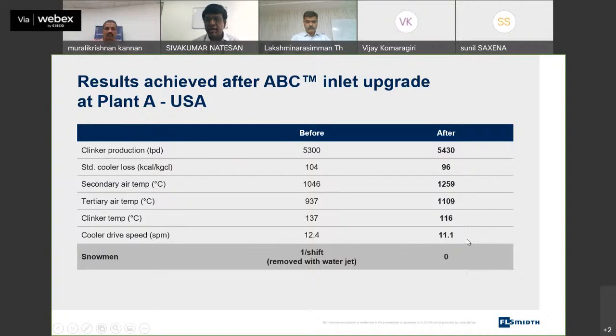That improves the wear rate of the cooler also, because we are able to achieve better production and better operating parameters, even with reduced speed of the cooler. We are able to allow the clinker bed to be formed at a larger bed depth without the fear of agglomeration and snowman. So that helps us to recuperate even better, and that gives a benefit on the parameters.